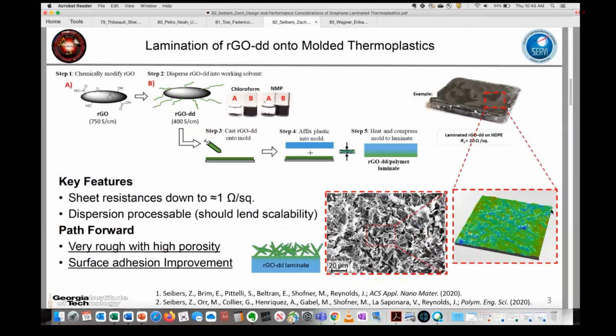So to look into this a little bit and give you some background about our work, we've made a chemically modified version of graphene that we can spray onto various surfaces. We can use less than a milligram per centimeter squared to achieve coatings that are down in the 1 to 20 ohm per square range quite regularly. Despite these benefits, there's a big roughness issue with this surface. And I think that this is a problem, but one of my scientific queries is how much of a problem is this? And that is how much does the roughness and the porosity of the surface really affect the performance in a dusty environment? And so if we go to the next slide,